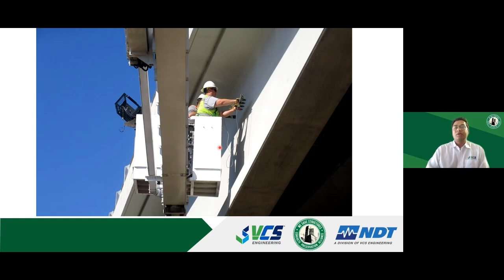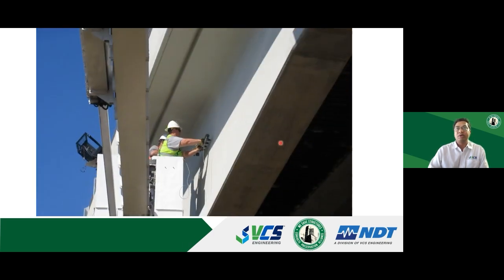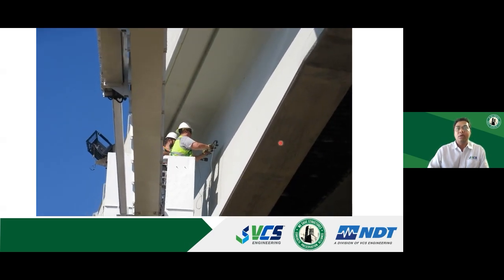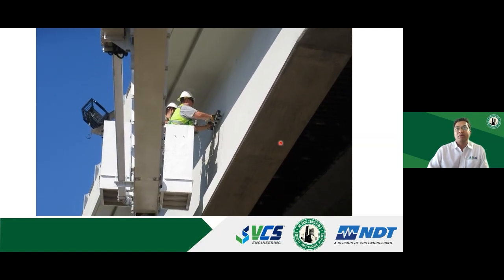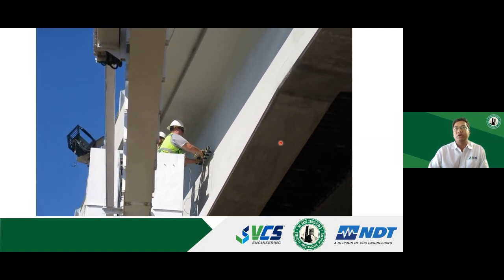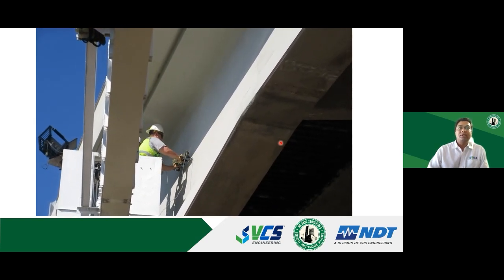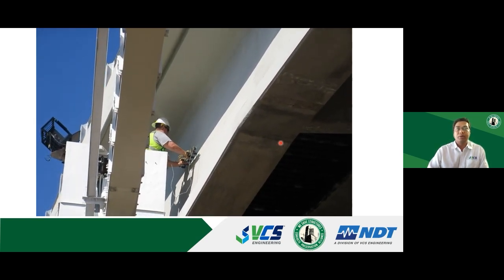Here is one of the videos from one of the projects we were working on, where you see a technician holding a sensor array, all 4 sensors, and he will place it on the concrete surface. This testing happens when you have already laid out the profile of the post-tensioning strand or duct on the concrete surface, and then you just follow the profile, make the impact and do the testing, and it goes something like this. So you make an impact, you place the sensor, make an impact, place the sensor, make an impact, and it collects the data while you're doing so. And you can see the pace of the testing, it goes pretty fast.